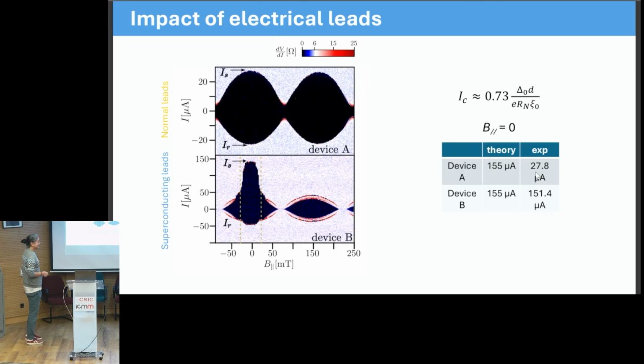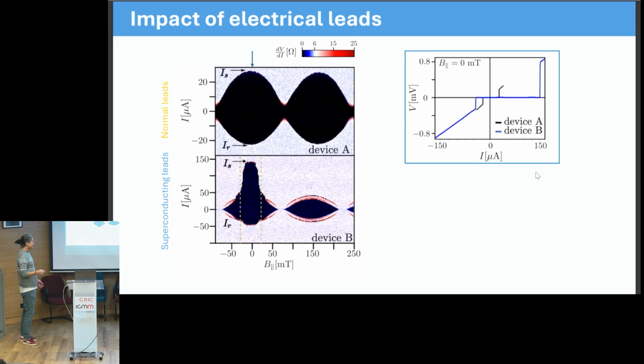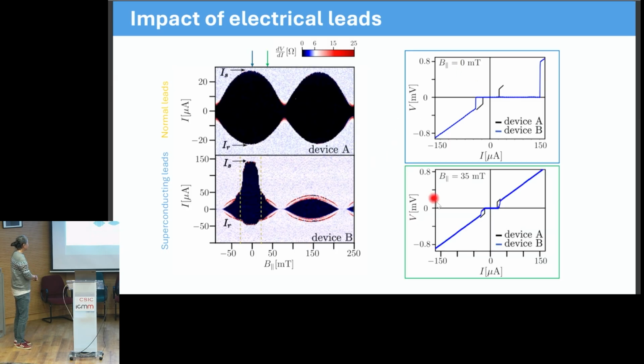This pointed to a strong impact from electrical leads, and we speculated this was due to the inverse proximity effect, that a normal electrical lead would impose on the superconducting aluminum. And this can be seen more dramatically if we plot line cuts. So this is done here at zero magnetic field, and we see a huge discrepancy in the critical current of one wire or the other. But then when we take another line cut at a finite magnetic field, over here, they are similar.